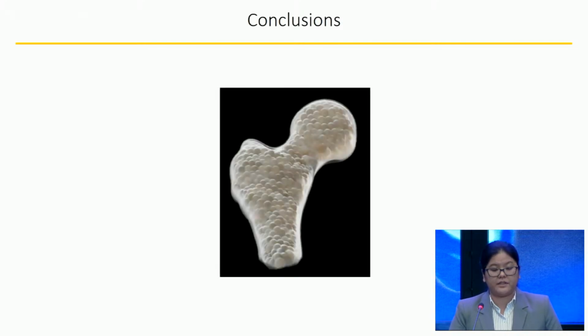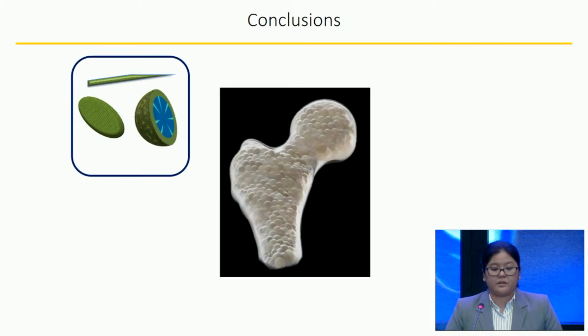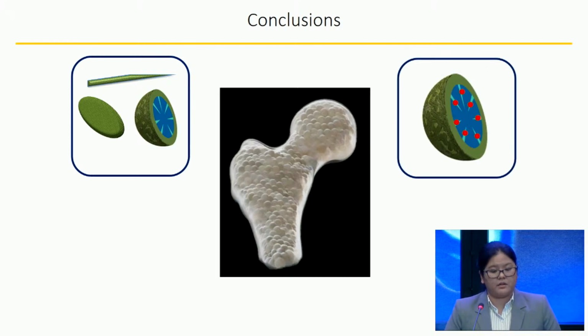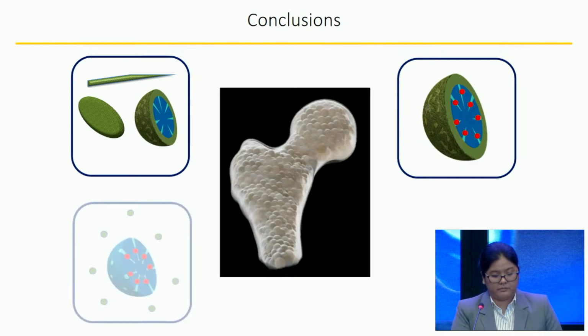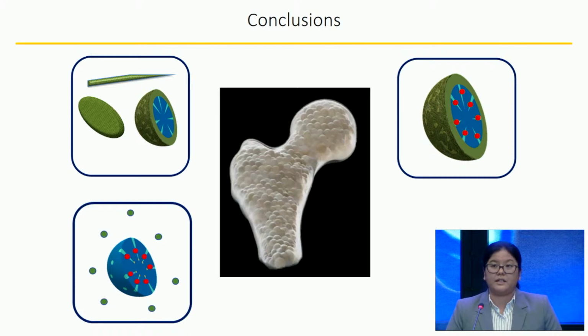In summary, this thesis demonstrates that osteogenic differentiation of the human mesenchymal stem cell is influenced by the shape of the calcium phosphate nanoparticle. Bioceramic nanoparticles can be used as an effective multiple ion delivery system to stimulate osteogenic stem cell differentiation. Zinc incorporation amount and release profile in association with the silica ion release are important factors in determining their bioactivity. Laser doping technique is a viable method to incorporate ions onto the bioceramic nanoparticle.